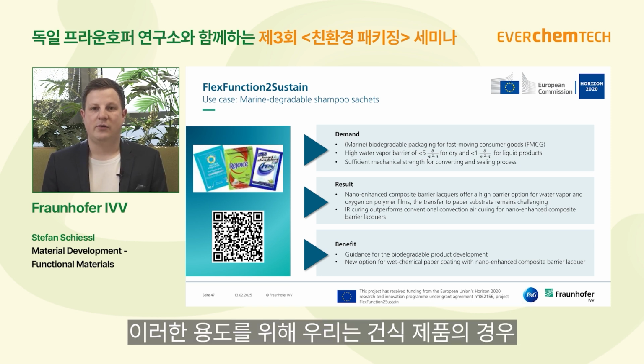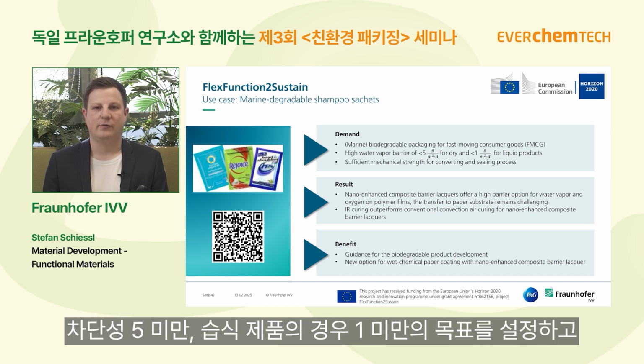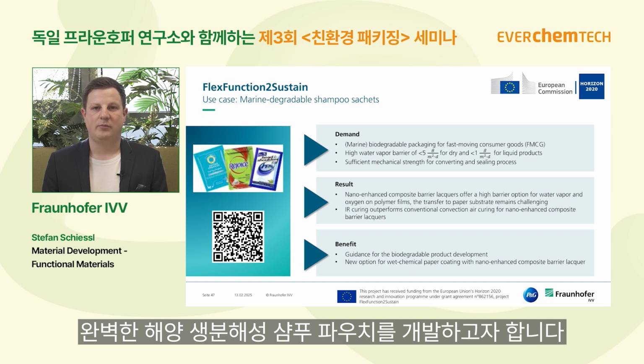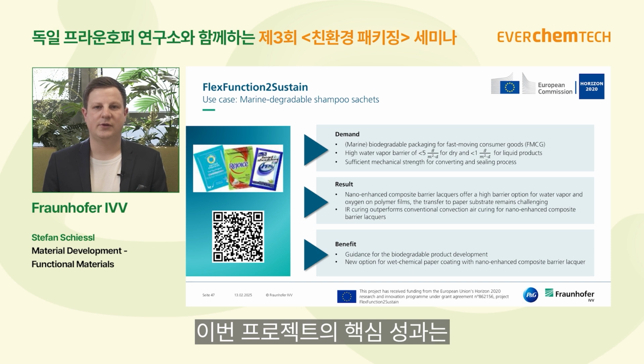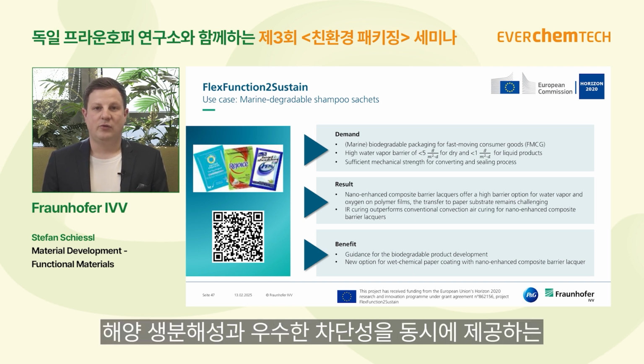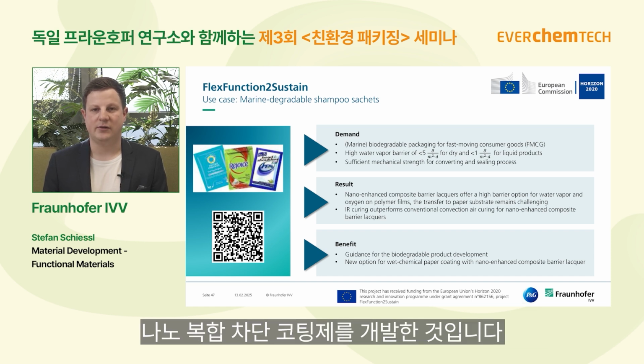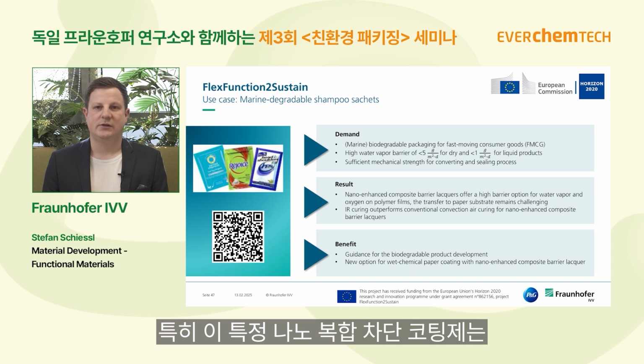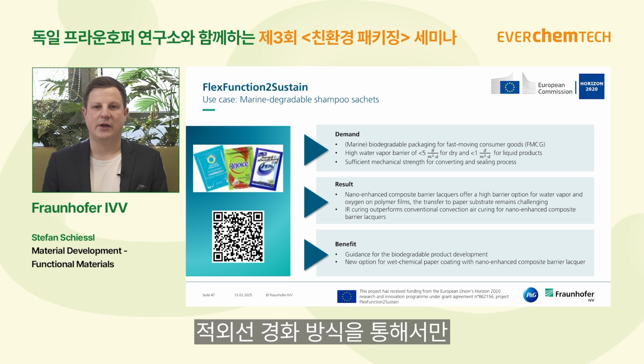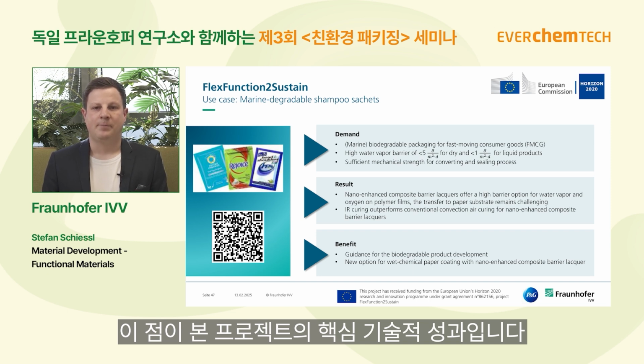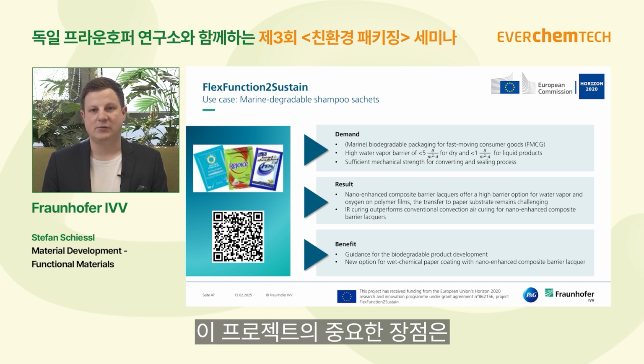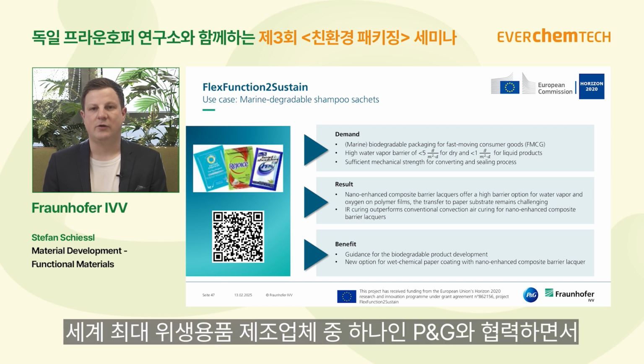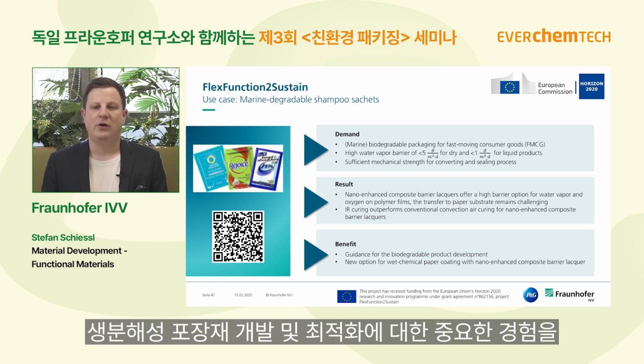We look for a barrier value that is below 5 for dry products and below 1 for wet products, and for a completely marine biodegradable shampoo sachet. The results we gained during this project, first of all, we introduced a nanocomposite barrier lacquer that can provide those properties, so marine biodegradability and the barrier properties, and we also learned as a result the special type of nanocomposite barrier lacquers is only able to be cured with IR curing, and that's, let's say, the key point of this project. And the benefit of projects like this is that we have a great view on one of the biggest hygienic product producers in the world, Procter & Gamble, and that we learned really well to work with such biodegradable options.